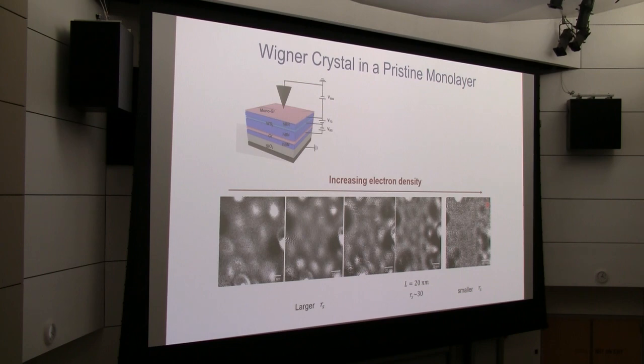So these are basically pinned by disorder. So even if they are not a perfect Wigner lattice, it is definitely a Wigner crystal. The electrons actually sit at a specific position for hours. So they really form a solid. And when you change the density of the electrons, going from left to right, you can see the Wigner crystal indeed has higher and higher density, but it still remains a solid, up to an electron separation on the order of 20 nanometers. So over here, the rs value is around 30. You can see the discreteness is becoming weaker.